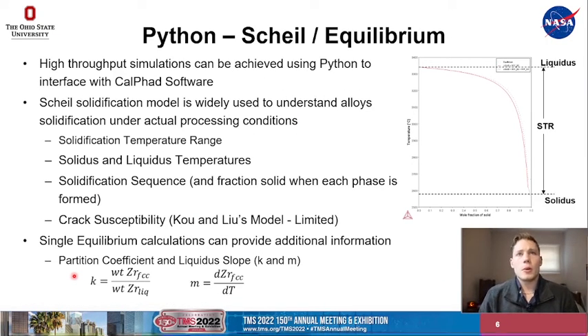We also used Python in order to interface with the thermodynamic software. This enabled us to do high throughput simulations to achieve the calculation speeds that I mentioned earlier, and two of the primary models that we used through Python were the Scheil solidification curves and single equilibrium calculations.